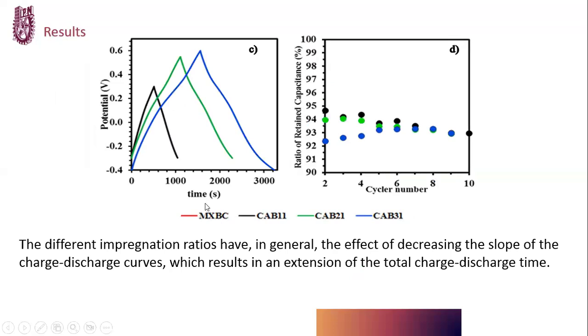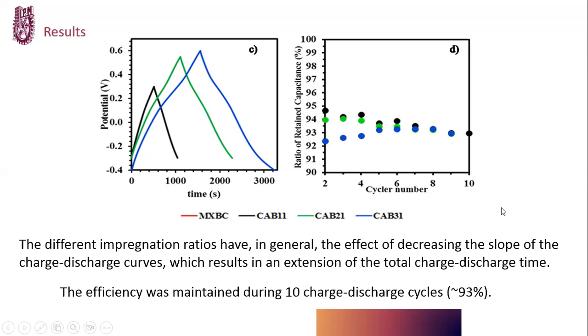Slightly distorted galvanostatic charge-discharge curves are shown for the cells of the activated carbons in this figure. The different impregnation ratios had, in general, the effect of decreasing the slope of the charge-discharge curves, which results in an extension of the total charge-discharge time. And the specific capacitance retention of the activated carbon electrodes after 10 charge-discharge cycles is approximately 93%.